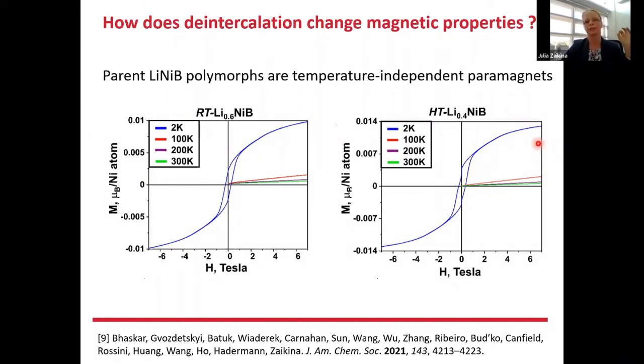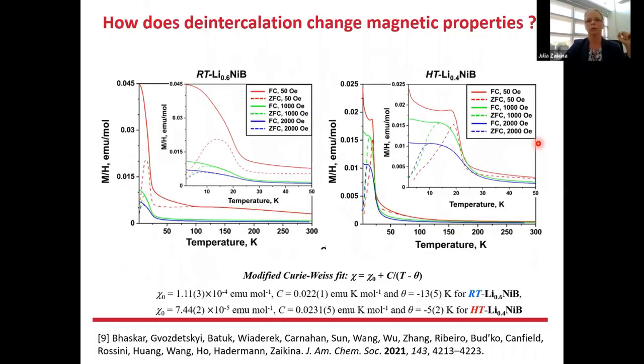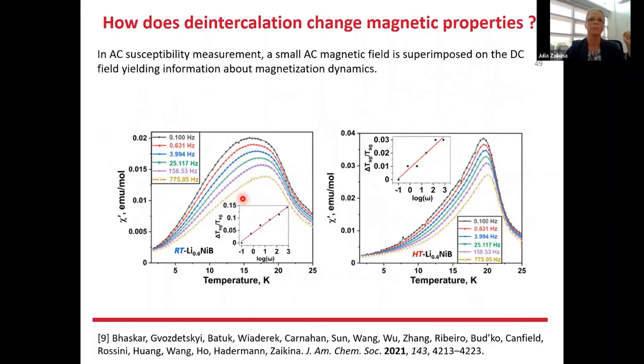but the deintercalation induces magnetic order at low temperatures. At temperatures below 24 Kelvin, we do see a magnetic transition, and this magnetic transition is of the spin glass type. We performed some AC susceptibility measurements to determine it.